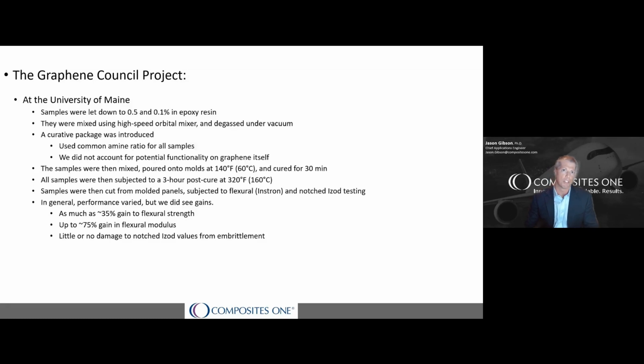We then poured the samples into a mold and cured at 140 degrees Fahrenheit for 30 minutes, and then followed that up by a 3-hour post-cure at 320 degrees Fahrenheit. Samples were then cut from the molded panels and tested for both flexural properties and impact toughness.